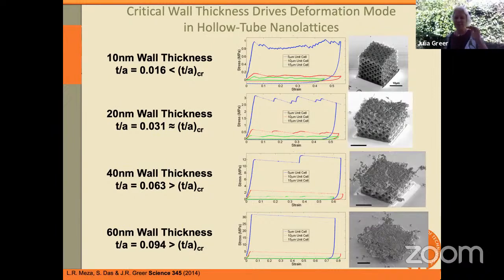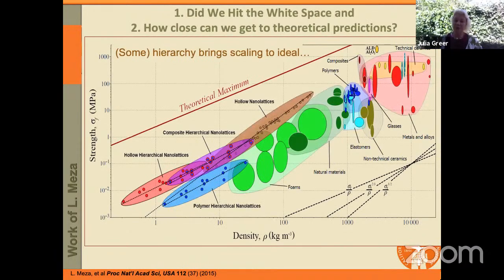Now, as we increase the wall thickness and get first to the critical thickness and then exceed this critical thickness, what you can see is that the deformation becomes a lot more jerky, a lot more catastrophic, and certainly the material is not able to recover after that. So what that tells us is that the answer must lie in mechanics, right? So let's see how close we got to this theoretical maximum and whether we got into this white space.